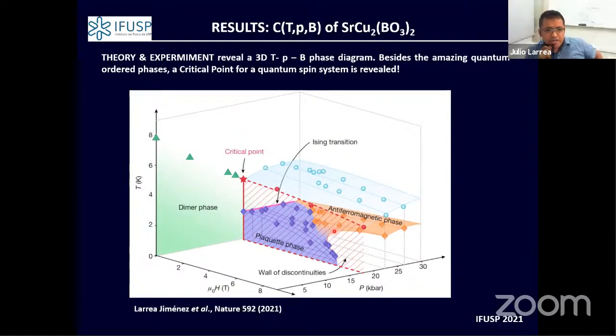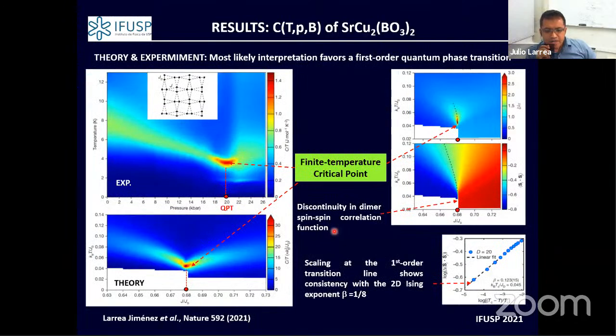Indeed, this is a very timely question, because something still pending to do is how this correlation can be mapped. For instance, one thing would be to have the spin-spin correlation in contact with a phonon bath, where you determine how this correlation changes with the phonon bath, in case there is some trend. But we still don't know exactly the answer to this question. This is a future experiment for sure that we have in mind, to design one experiment that measures this spin-spin correlation more directly.